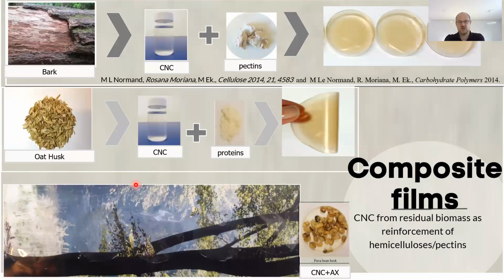Another way around it is to look at composites. This is work, I got this slide from Rosana Moriana from her time at KTH, when she did research there. She looked at bark and oat husks to get pectins and proteins, and mixed them with CNC. The advantage they could show was better barrier properties. Nanocellulose is a little bit porous as such, and these kinds of materials would fill out these pores. It would improve the oxygen barrier, even if it's something that's not a good oxygen barrier itself. And they would have a better water resistance too. So here they could make nanocomposites that would work a lot better.